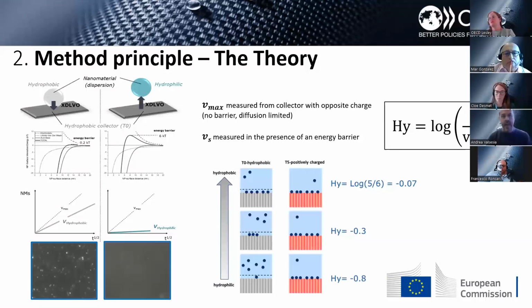What happens if I have a hydrophilic nanomaterial? In this case, the extended DLVO theory tells us there is a relatively high energy barrier for the particle to get in contact with the surface, around a few kT values. This means the thermal energy is not enough to make the particle overcome the energy barrier. The particle prefers to stay in the water dispersion, and the relative binding rate of particles on the collector is really low, translated into a very, very low binding rate, almost zero binding rate of particles to the collector.